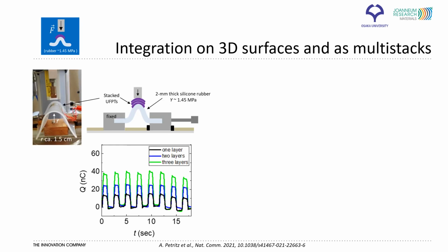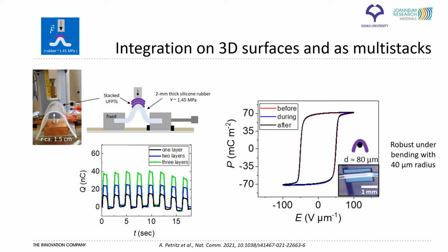Moreover, the small thickness allows to stack multiple sensors on one another and thus multiply the sensor response, and to do that also on a 3D shaped object like this pre-bent silicone rubber. The mechanical robustness of the ultra-flexible sensors is exceptional. The polarization hysteresis remains completely unchanged during bending around an only 80 micrometer thick wire.